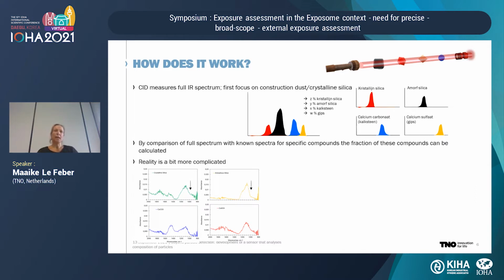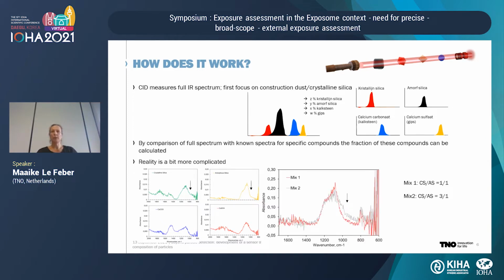And to verify whether we can distinguish between the two, we took the spectra of 2 mixtures. Mixture 1 contains equal crystalline silica and amorphous silica, while mixture 2 contains mainly crystalline silica. And as you can see, again, at the arrow, the slope of the gray spectrum is less steep than the red one. So yes, it is possible, even though it's not a very specific peak for the different substances, to distinguish between the substances from the spectra.